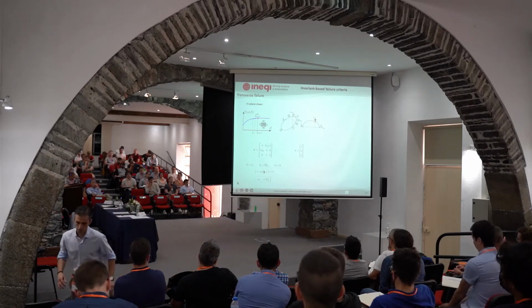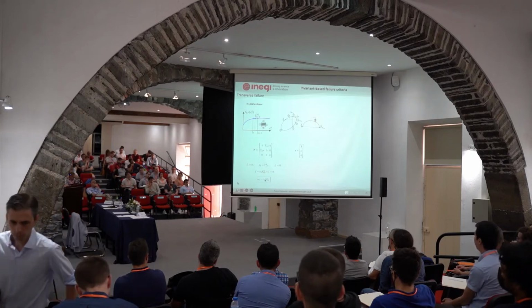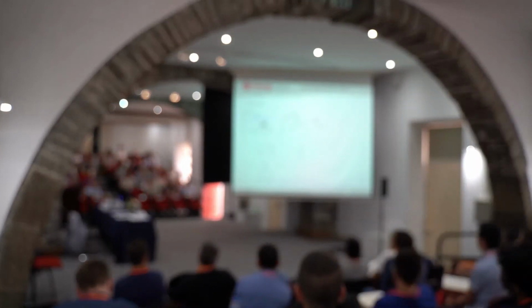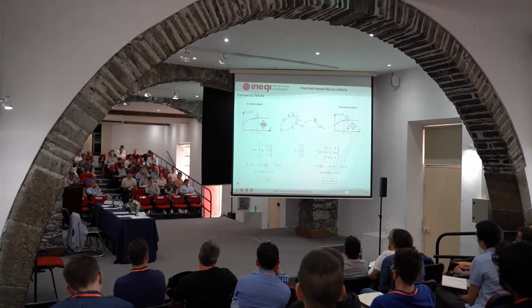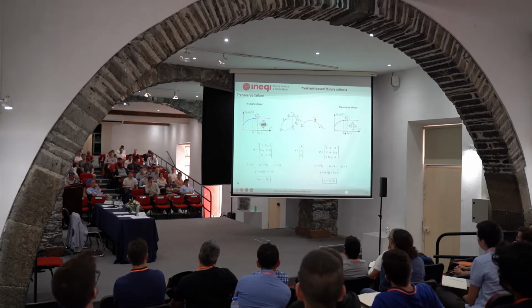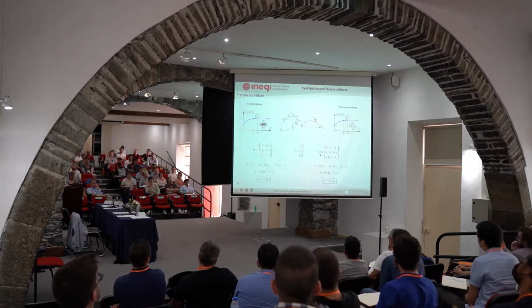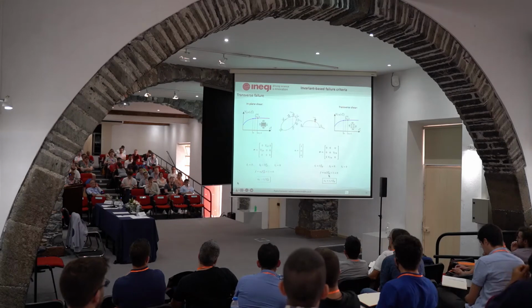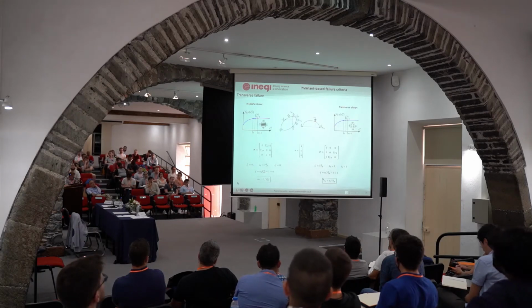So you are loading in this direction, okay? And when you reach failure, you obtain alpha 2 as 1 over the square root of this stress value over there. Okay, and we have alpha 2 identified. Now, if you want to apply transverse shear, which is more complicated to do experimentally, this is again your stress tensor. A is the same, and now the only non-zero invariant is I1. So I do the same as before. When I get failure in the material, I obtain alpha 1 from this equation. So you can see that it's very easy to identify the model.